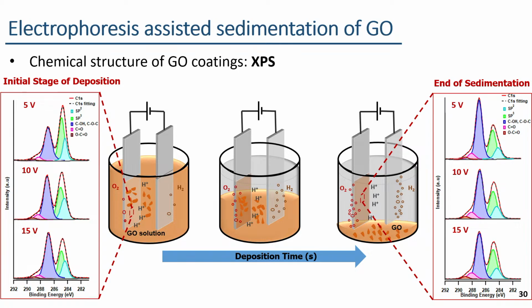a smaller amount of basal plane oxygen functionalities. These basal plane oxygen functionalities are shown in these blue color peaks. So, this smaller amount of oxygen functionalities can be observed in the GO coatings obtained at the initial stage of deposition at low voltages when compared to those at higher potentials. At the same time, the GO coatings obtained at the end of the sedimentation process show a high amount of basal plane oxygen functionalities.